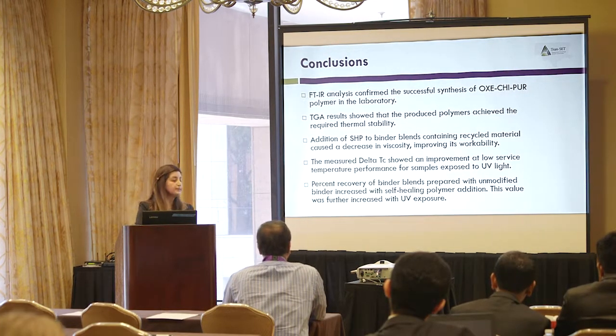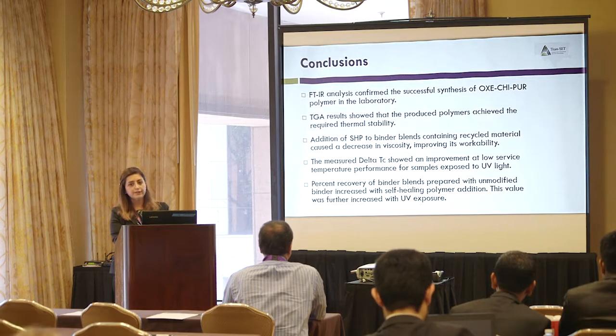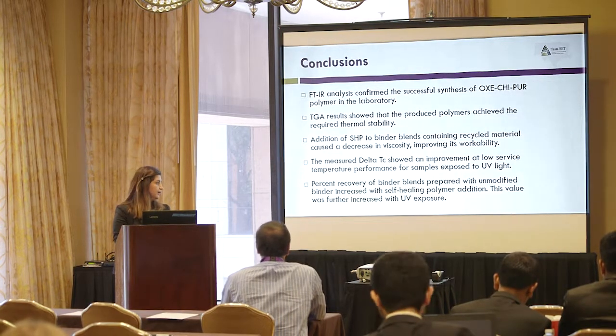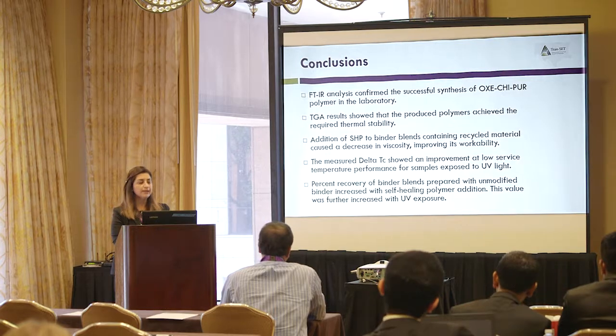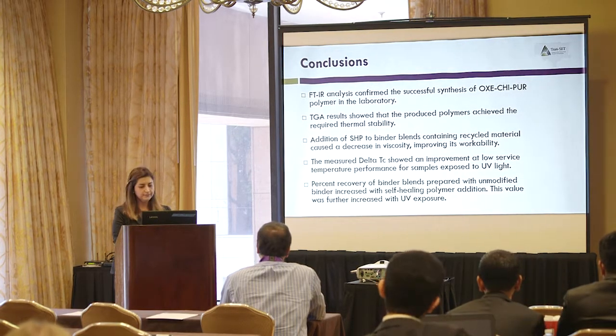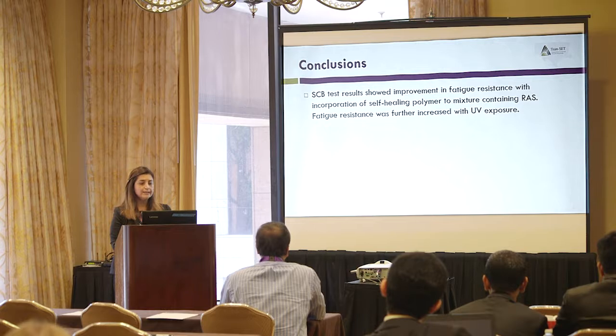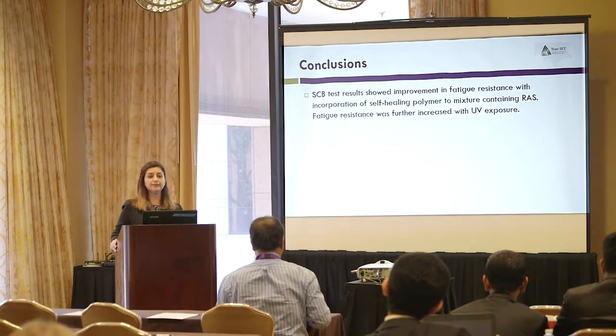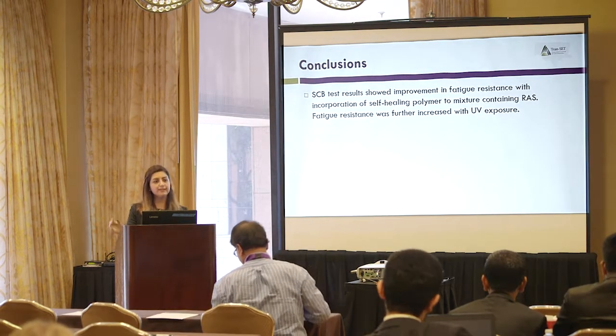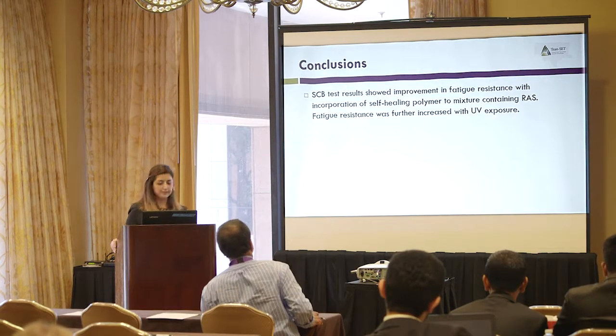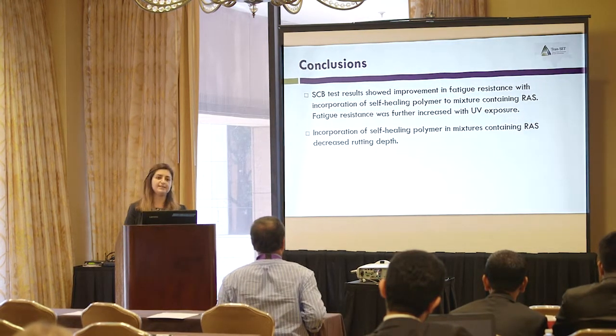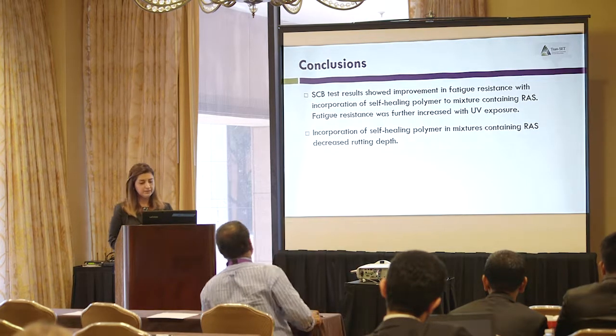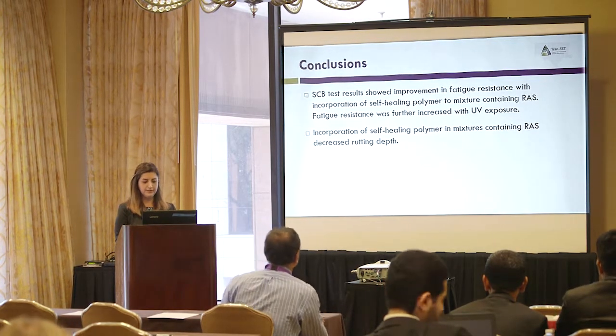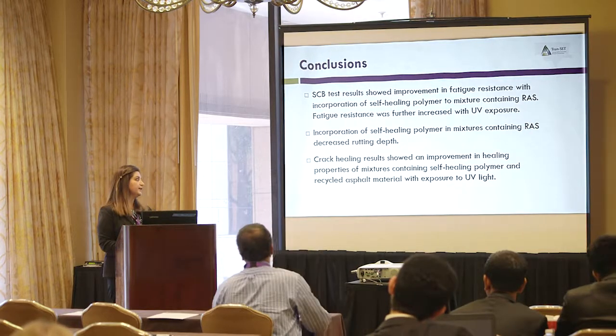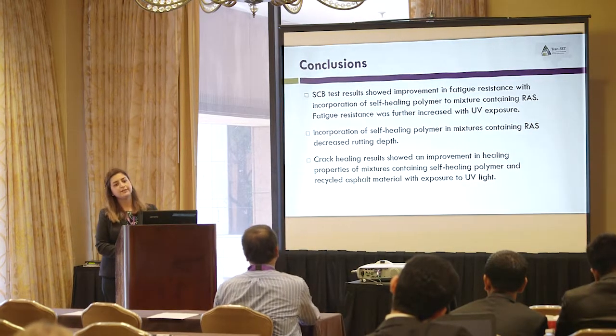Also, we were able to see improvement in elastic recovery of the unmodified binder with adding self-healing polymer and exposing samples to UV light. SCB results showed improvement in performance of the mixture containing RAS. With adding self-healing polymer and exposing them to UV light, we were able to see the same result from the rutting test, LWT, and also by performing self-healing tests by monitoring cracks under the rectangular beam.